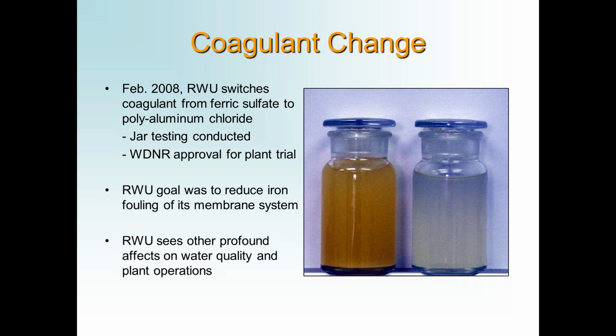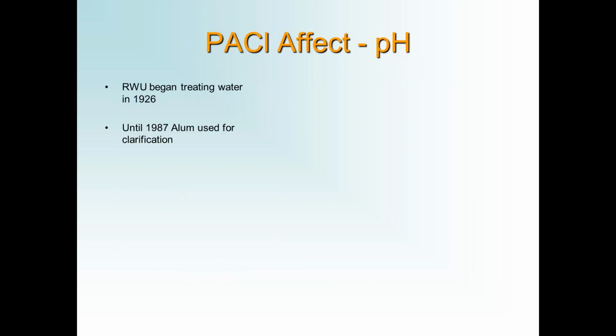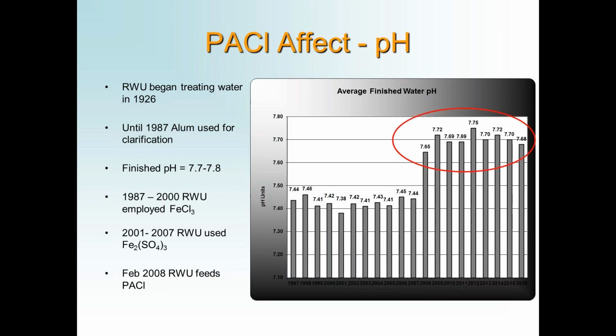Fortunately for us, we found out that the switchover from the iron salts to polyaluminum chloride provided a number of other benefits in our treatment process and effects on water quality. One of the things we noticed was the effect on pH. Historically, Racine had been an alum plant. We switched in 1987 from an alum to an iron salt.